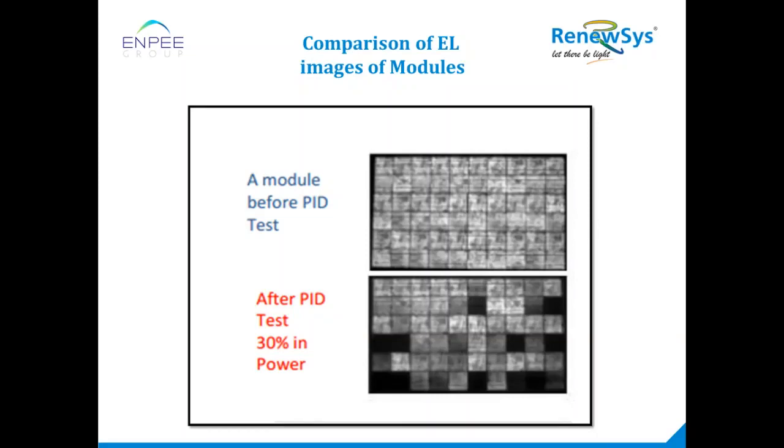If you take a glass-to-glass module, we have two rigid surfaces on the top and the back. So some module manufacturers will not have the frame, but there are other issues. In glass-to-glass modules also, nowadays a thinner frame is coming into the picture, but an aluminum frame is there. The moment we have a frame, the effect is the same on both glass-to-glass as well as glass-to-backsheet modules. If glass-to-glass modules do not have a frame, then the problem of PID is not there in glass-to-glass modules.